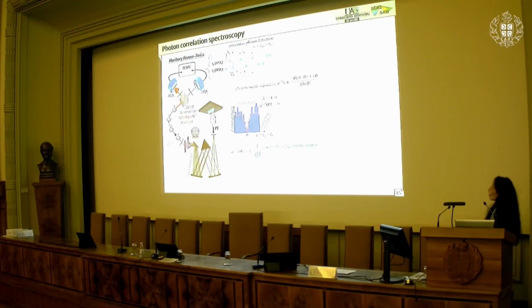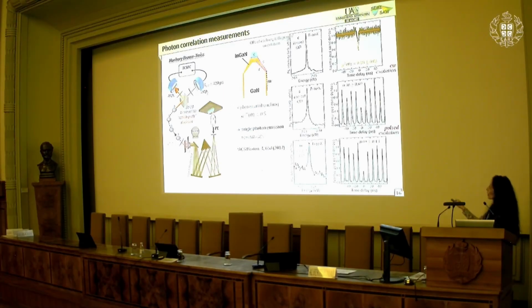So in the case of a truly single photon emitter, as is seen here, what we observe is a complete reduction of the g2 function at zero time delay between consecutive photon detections at both detectors. And indeed, for all three types of quantum dots, we do see such a reduction of the coincidence rate at zero time delay, which suggests that the probability of simultaneous multiple emission, or emission of multiple single photons, is significantly reduced.